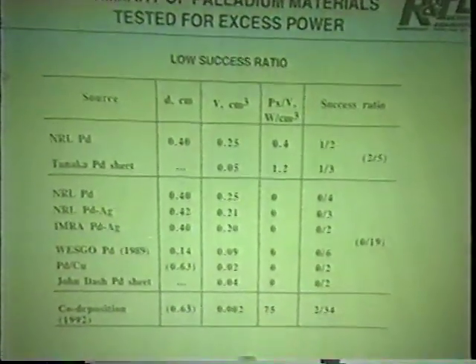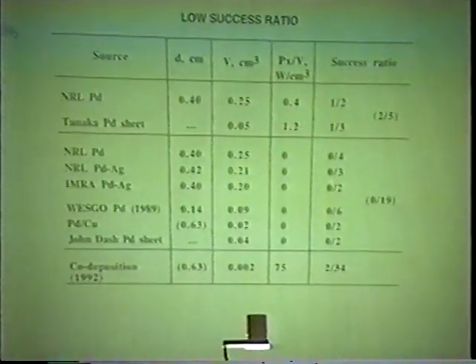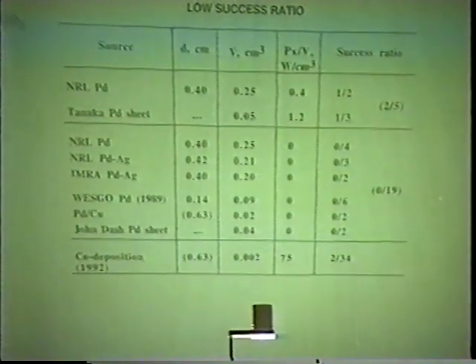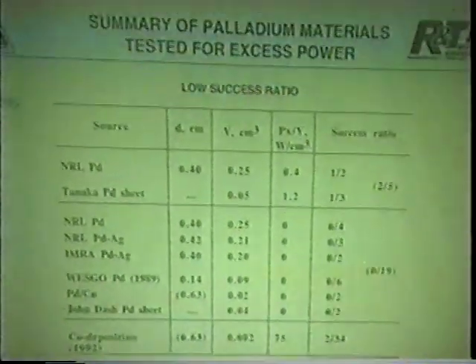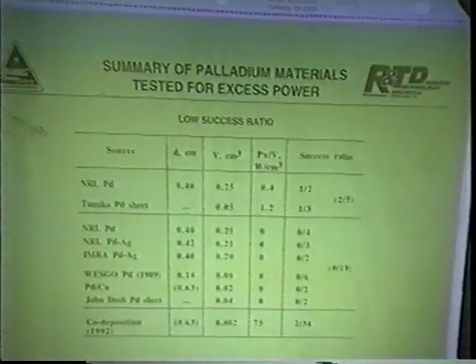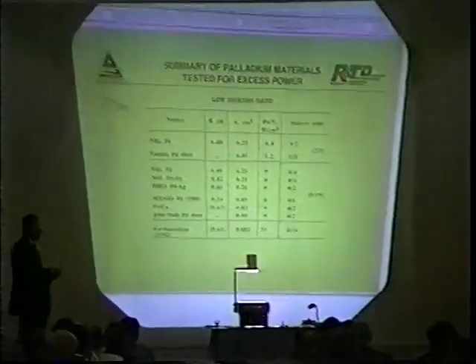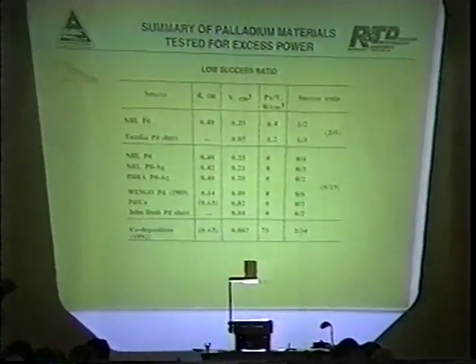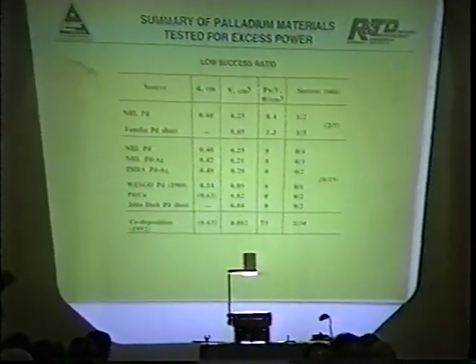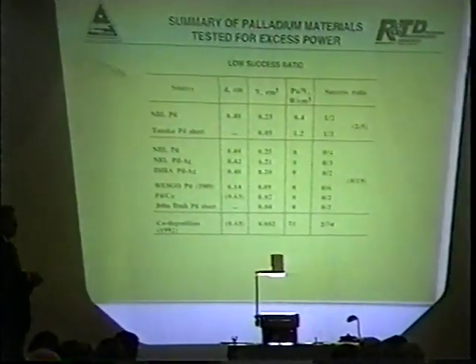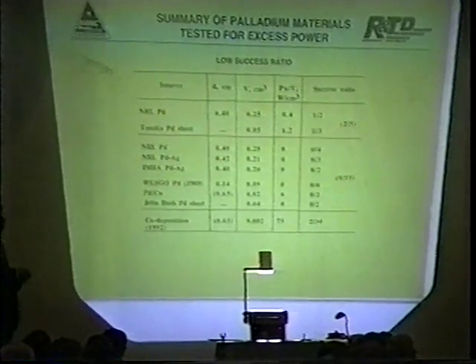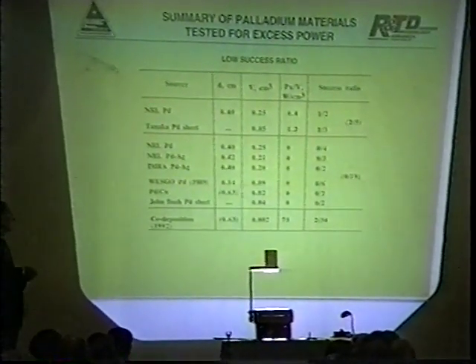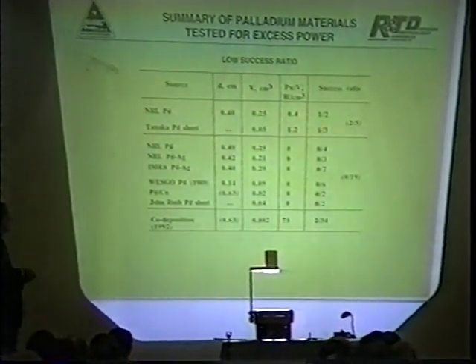Another source of the palladium. If you look through here, we have no successes out of 19 experiments. So we have a definite grouping where we have poor material, and often this shows poor loading. We have a poor success rate for excess heat. And it's hard to understand how this could happen by chance. How would we get this grouping if we're just making calorimetric errors? To me, it's almost impossible that we get this type of grouping.